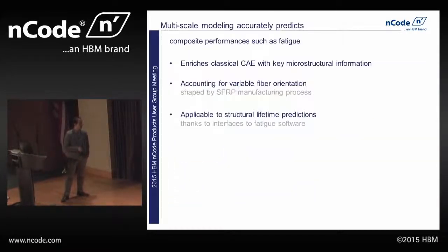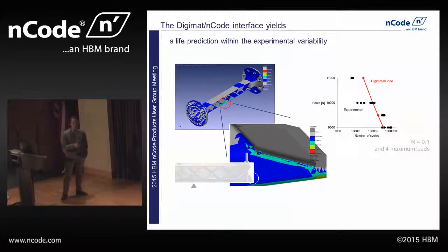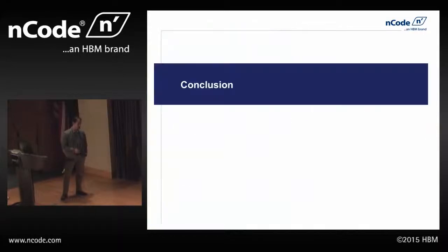So in conclusion, multi-scale material modeling, such as Digimat, allows us to accurately predict composite performances, such as fatigue. It allows us to enrich the classical CAE methodology with some key microstructural information, that really being the fiber orientations and how that affects the mechanical properties. And by accounting for the variable fiber orientation shaped by that manufacturing process, we can really predict the fatigue life of actual engineering components. And this is something that we've demonstrated not just in these simple lab-type test cases, but on real engineering components used in the automotive industry today.